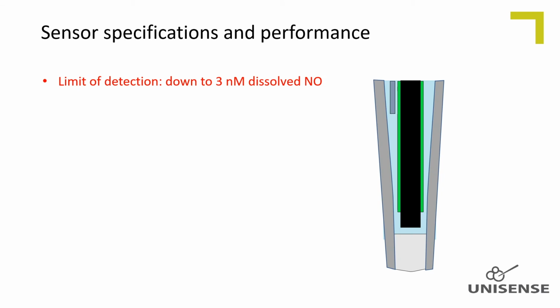I will now turn to the actual performance and specifications of the nitric oxide sensors and give some comments to them. Recall that these specs are only guaranteed with use of a Unisense meter. The detection limit is stated to be down to 2 to 3 nanomolar dissolved nitric oxide for the larger versions of the nitric oxide sensor. However, the detection limit is strongly influenced by the application in question. The smallest sensor, version NO15, generates, due to the small tip diameter, a much smaller current than the larger versions, and thus the detection limit is not better than 20 to 30 nanomolar.